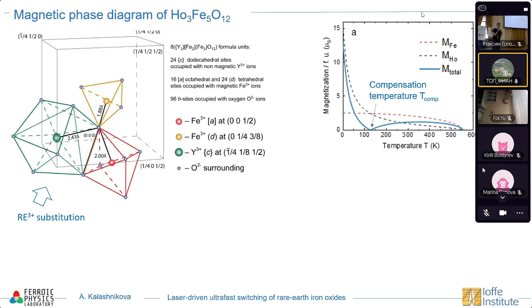in opposite directions. And what is most interesting, there is a very different temperature dependence of magnetization of, for example, holmium or other rare earths, shown by the black dashed curve, and of magnetization of iron, which is shown by the red curve. So there is a compensation temperature. Basically, it means that here, for example, if we apply a magnetic field, the magnetization of holmium will be pointing along the field, and magnetization of iron will be opposite, and here it will be just reversed.